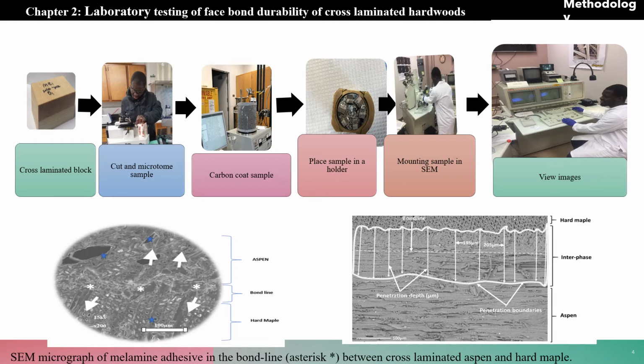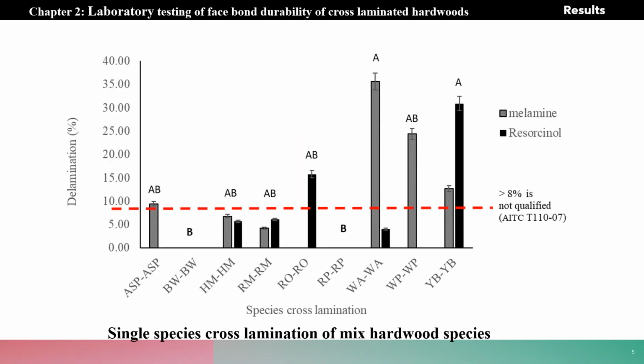And what happens is we determine how much the adhesive seeps into the wood cell lumen. So adhesives that are fully filled are considered the rate at which it penetrates. And so we trace using an image analysis tool like ImageJ to determine how much it seeps into the wood, to determine the maximum adhesive penetration.